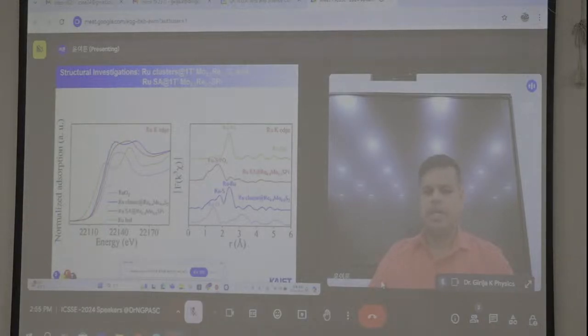It is also proved by the XANES analysis. You can see usually for the cluster, the blue one, the oxidation state will be lower, close to maybe 1. But when going through the transformation of the cluster to single atom, the oxidation state is increased. And I told you the blue one is cluster because the majority of ruthenium is bonded. But in case of our optimal catalyst, you can see there is not much bonding, only a lower shift, below 2. Then I can claim that this may be bonded to the sulfur, there is no cluster formation because 100% is transformed from the cluster to single atom via this technology.